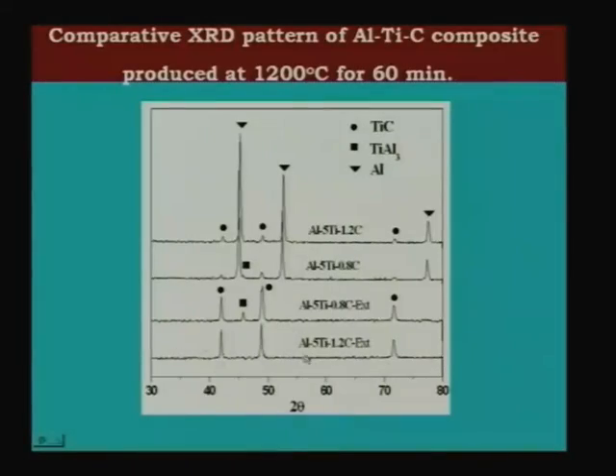If it is only TiC, you will see this kind of a situation, all the peaks will be only TiC peaks. From that you can clearly say that there is no TiAl3, and if you go to 0.8 you can see this, and from the ratio of these peaks one can find out how much of TiC is there and how much of TiAl3 is there. So, the weight fraction of TiC and TiAl3 in the composite can be found out from this kind of extraction experiments. Whenever you are working on composites, this is the best way to find out what is the volume fraction,